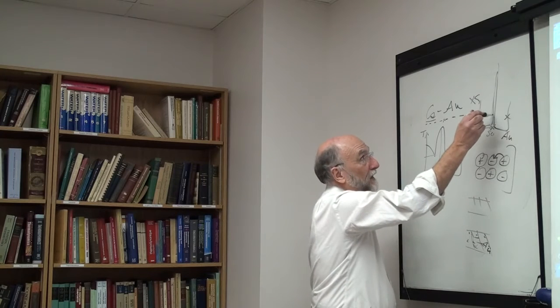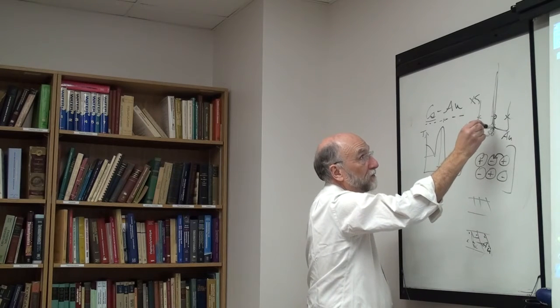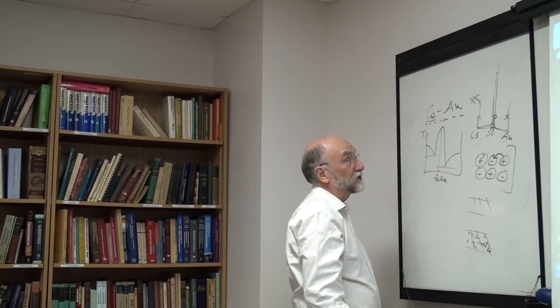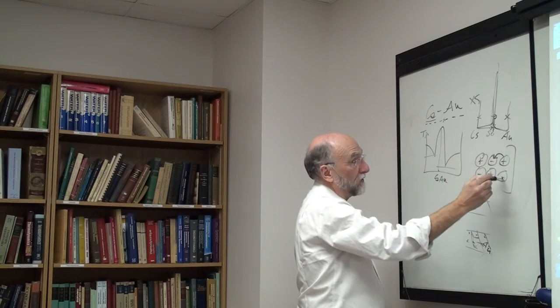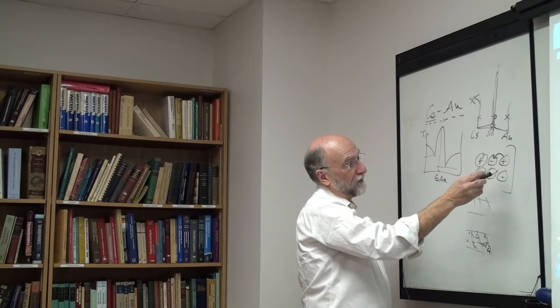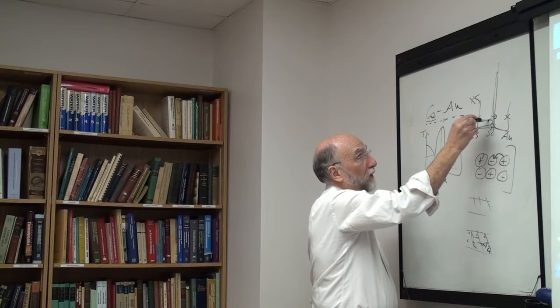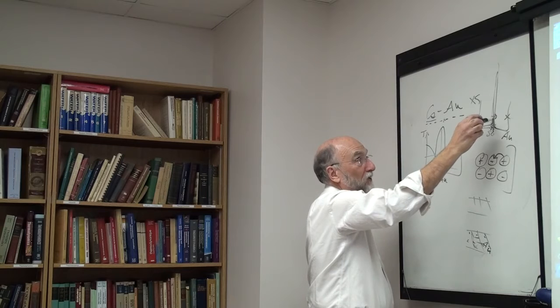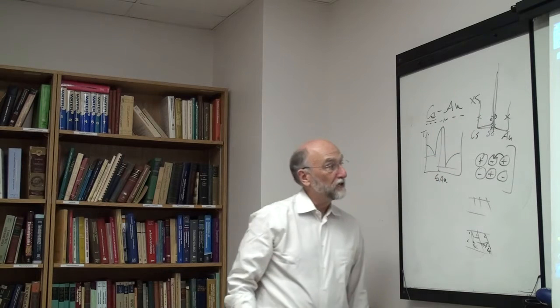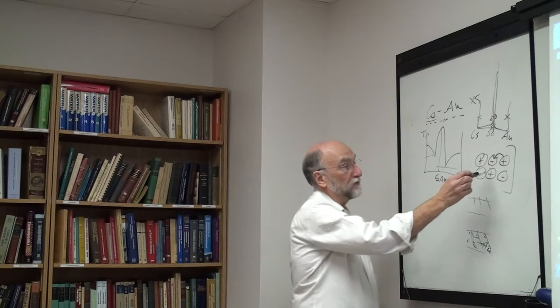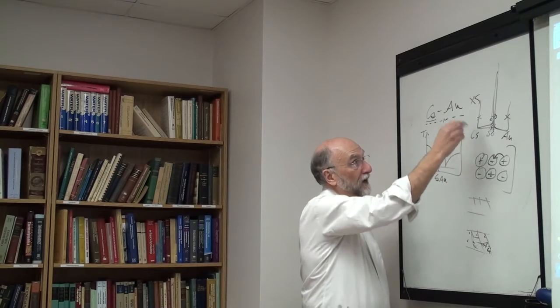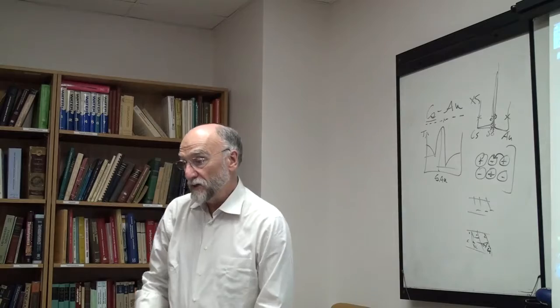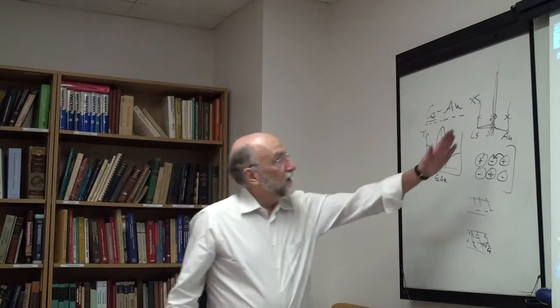As you get away from 50-50, let's put it this way, if you're at 50-50, you have cesium ions and gold ions. As you go a little bit to the left, you're adding additional cesium. The cesium goes in to form an ion, and the electron that it gives up goes up here into the conduction band, and essentially becomes a free electron, and you get an N-type semiconductor.